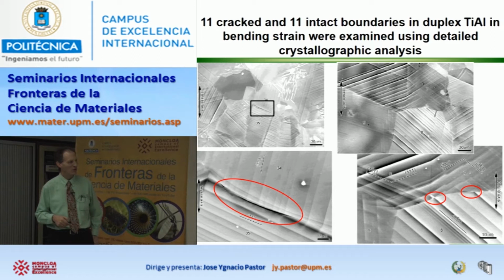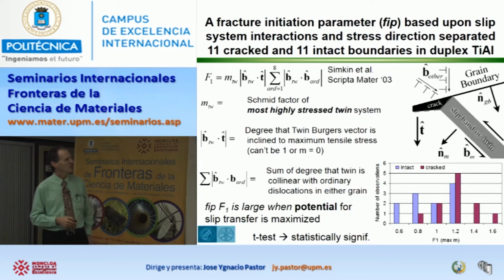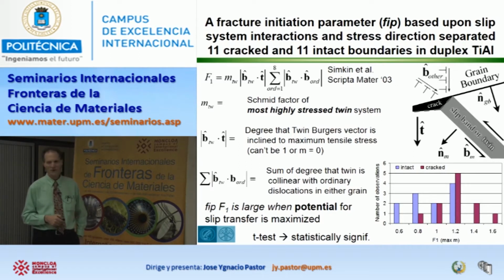And they tend to be correlated with these mechanical twins, right? Where a mechanical twin interacts with a grain boundary, in some cases, we get cracks. So the question is, why do we get cracks in some places but not others? And can we figure out why? So here's the model that we worked through to figure this out. It's a little bit complicated, but I'll try to give you the sense of it without going into too much detail.